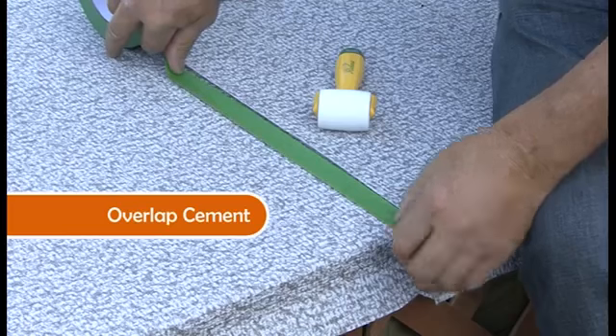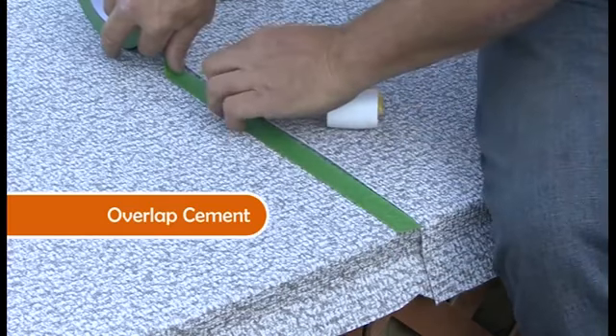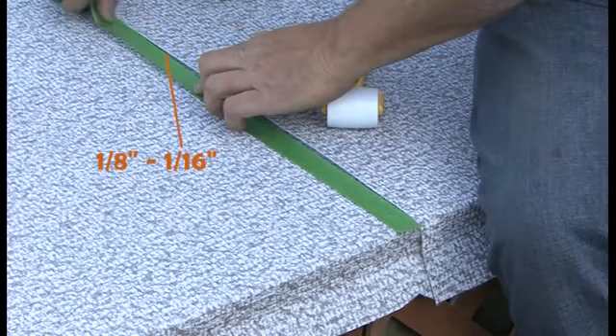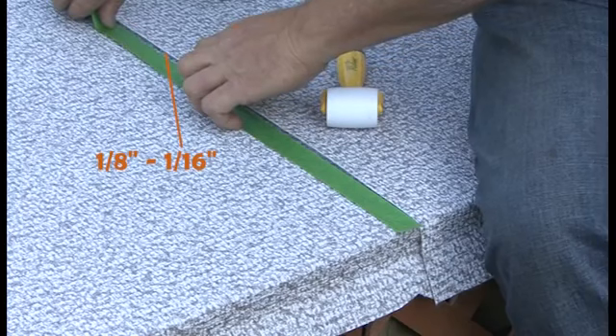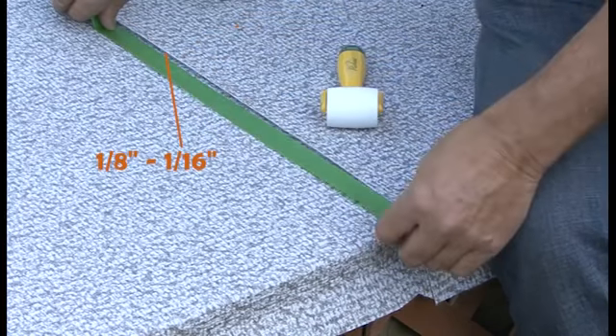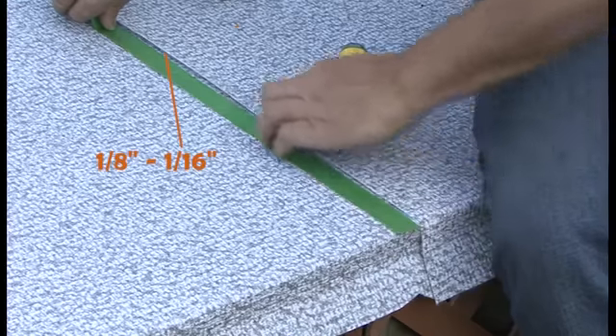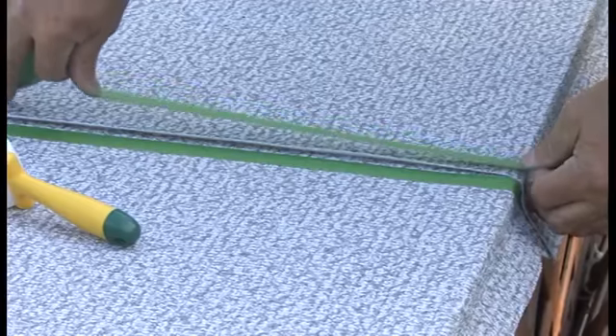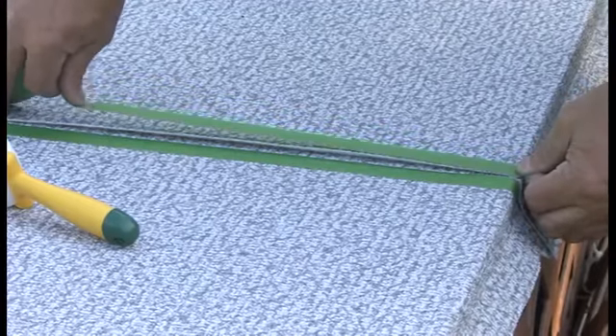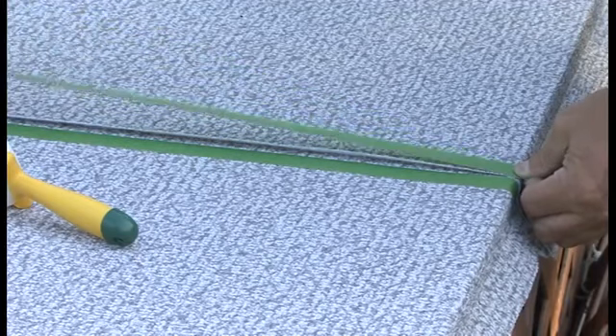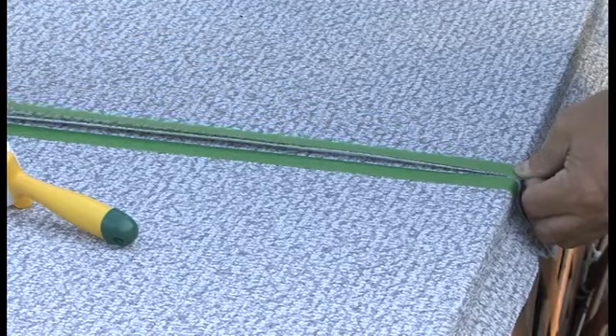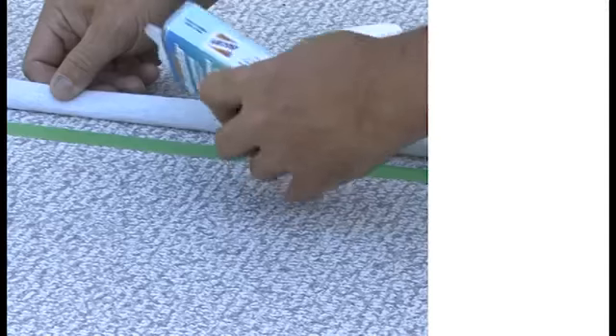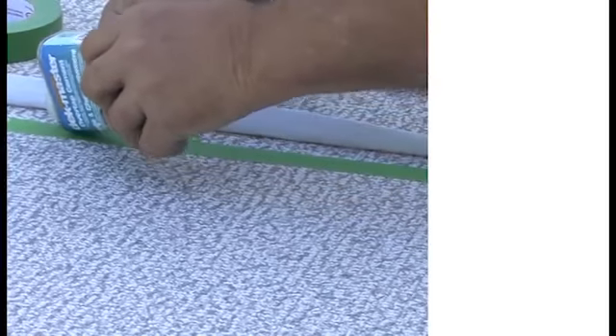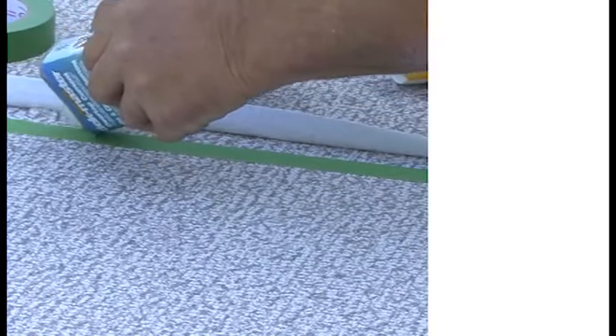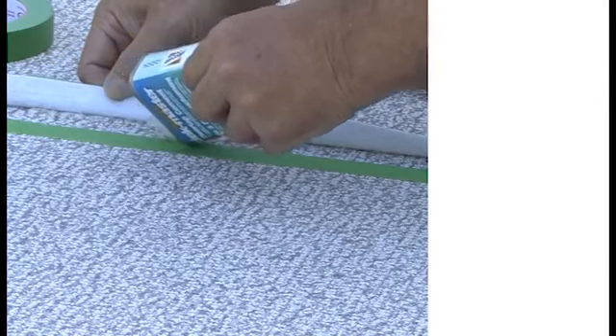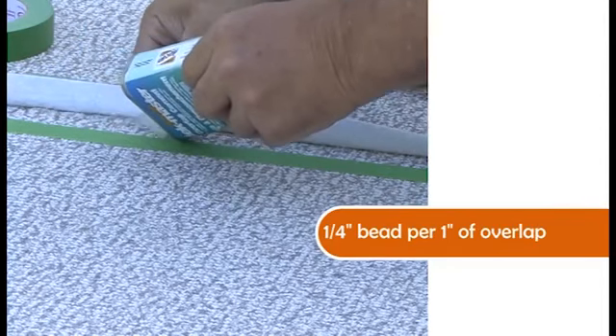For the overlap cement method, place a fresh piece of 1-inch masking tape 1/8 to 1/16 of an inch away from the overlapping edge. This is to catch the overlap cement as it comes out from under the overlap. As an option, you may also place a strip of masking tape down the top piece of vinyl to protect it from getting overlap cement overspill from the roller. With the nozzle on, squeeze the overlap cement under the 1-inch seam at the rate of 1/4 inch bead per 1 inch of overlap.